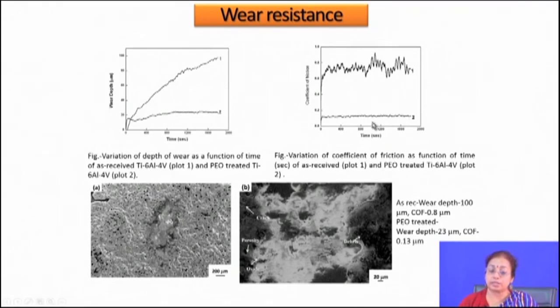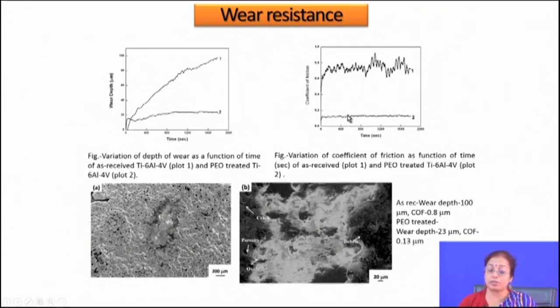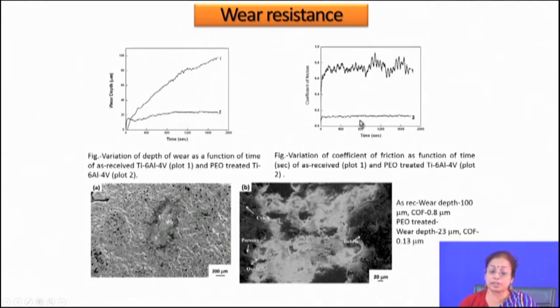There is significant improvement in wear resistance, which is typical for this oxide layer — because of the presence of the oxide layer the wear and corrosion resistance properties increase. Another interesting feature is a decrease in the coefficient of friction. This decrease in coefficient of friction was mainly because of the formation of the oxide film on the surface. If you use synovial fluid while doing a wear test, the coefficient of friction decreases further.